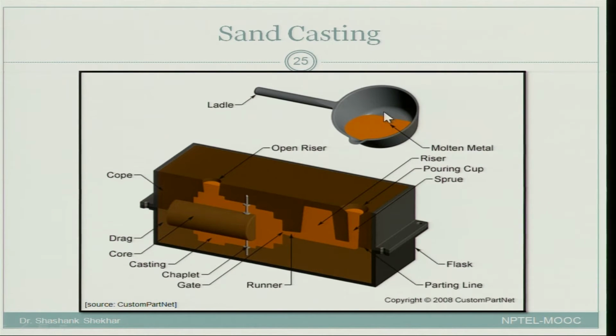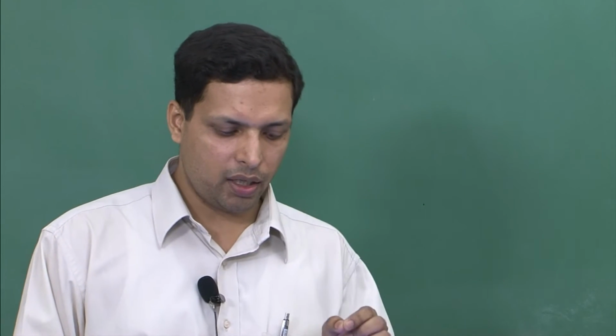So this is a simple way to understand sand casting. What you look at in the brown parts are actually the sand, and you put that sand around the pattern and hammer it to ensure that the sand takes the shape around the pattern. And once the pattern has been formed into the sand, you take away the two flasks, the bottom part and the top flask, and then take out the pattern slowly from inside.